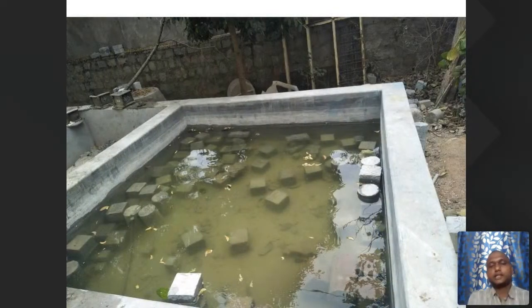This is the curing tank. Once you dismantle all your cubes, cylinders, beams or prisms, we have to cure them up to 28 days, or 60 days, 90 days, 180 days, or 365 days. But I did everything up to 365 days. That means one year. One year of curing in the same tank is very difficult, so I removed the water every 10 or 15 days and poured fresh water for curing purposes. This is a very important thing.